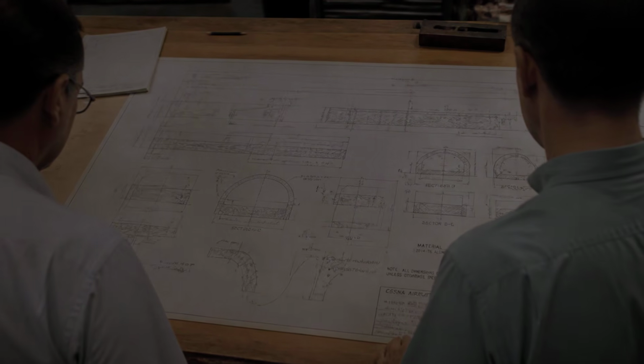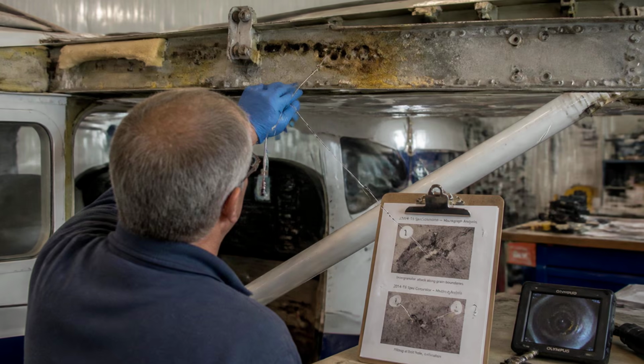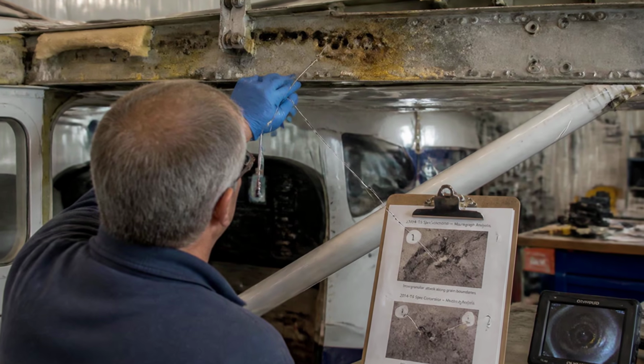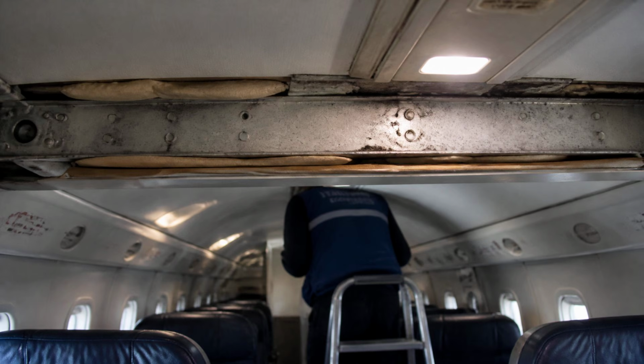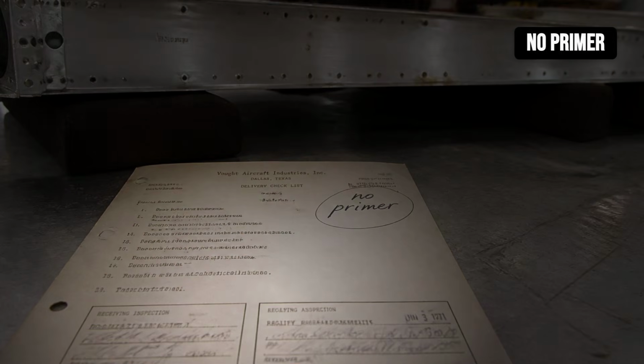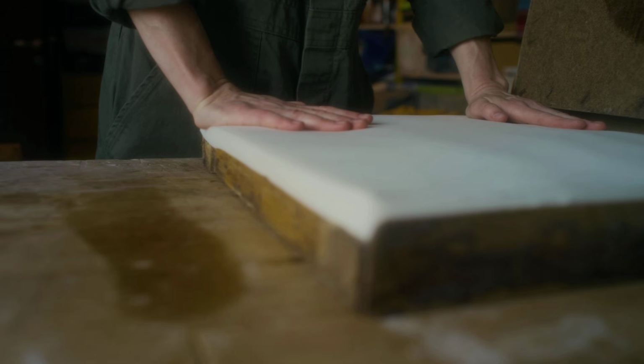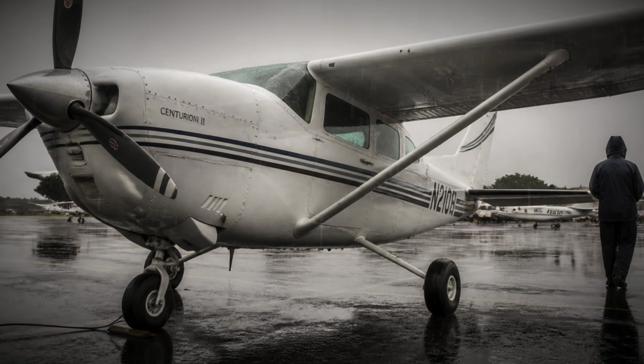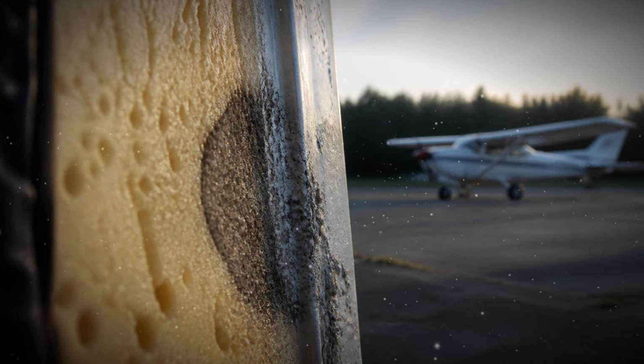Cessna built a single load path forged spar that was vulnerable to exactly this corrosion. They installed it in the top of a pressurized cabin. They delivered it with no primer and no corrosion protection, and they padded it with foam that would hold moisture against the bare metal for the next 40 years. The 210 sits on the ramp. It rains, the cabin dries, the foam stays wet. It stayed wet for decades.